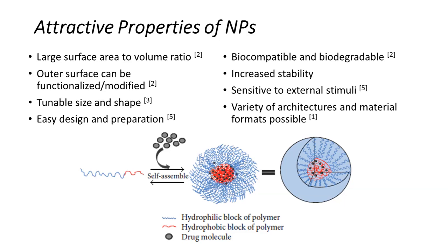You simply start with an amphiphilic molecule consisting of two different polymer blocks, one hydrophobic block and one hydrophilic block. You place them in a solution, and they self-assemble around the drug that you have in the solution, and that's how you can create these micellar structures that encapsulate therapeutics for cancer treatment.